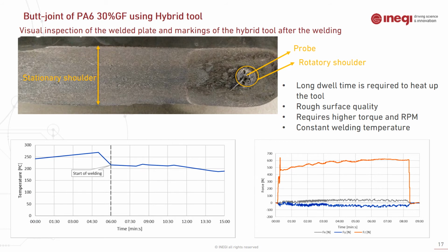In this slide you can see the visual inspection of the welded plate using the hybrid tool. The different marking of the welded plate is shown. For example, the stationary shoulder effect, as you can see, also the rotating shoulder effect and the probe effect. The surface quality was poor compared to the PEEK stationary shoulder, but this can be solved by coating the stationary shoulder.